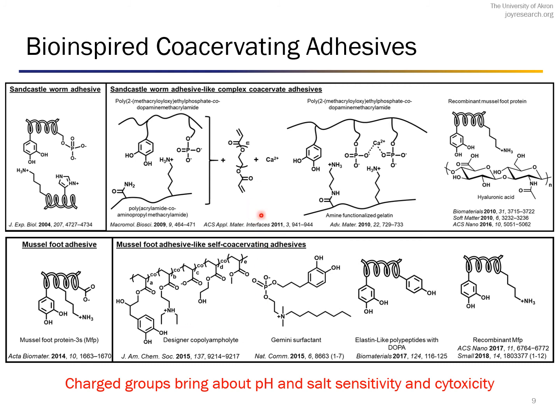Unfortunately, both these approaches still require the presence of cationic or anionic polymers, which have high cytotoxicity and high pH and salt sensitivity. The problem with these three is in a real life situation, where if you are using such adhesives for tissue adhesion purposes, it is a wet and dynamic environment where the pH and salt is not balanced always. In such cases, these polymers may not be effective. Hence, there's a need for adhesives which can be coacervated without the presence of a secondary component, pH or salt.